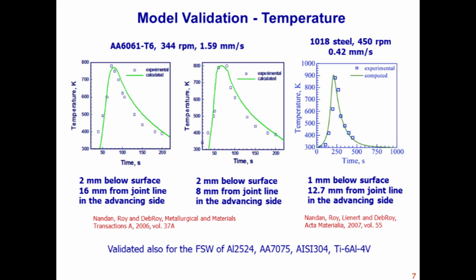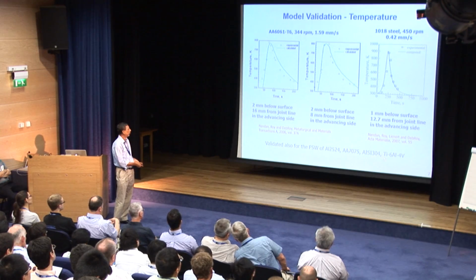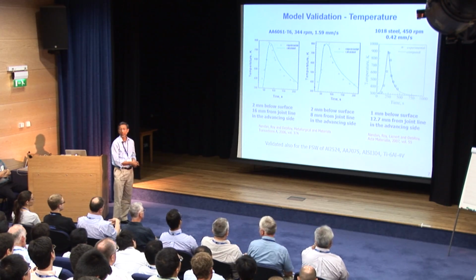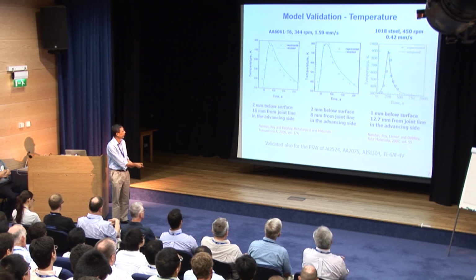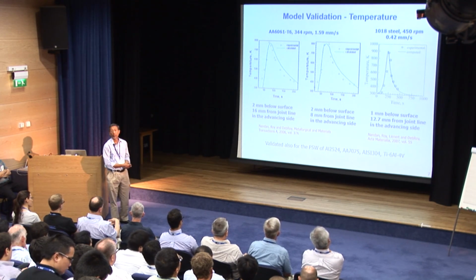So let me show you what those results look like. First thing is temperature field. And from the temperature field, we can calculate the heating and cooling rates and also time temperature plots. We have done that for a wide variety of materials, ranging from aluminum alloys to stainless steels with very low thermal conductivity, and also titanium 6 aluminum 4 vanadium alloys.